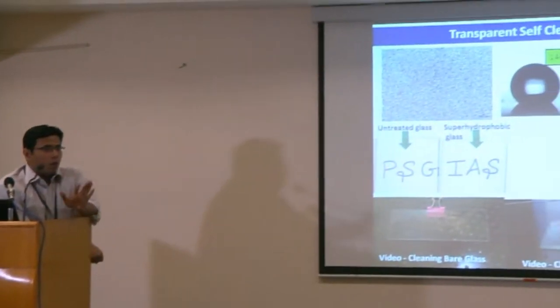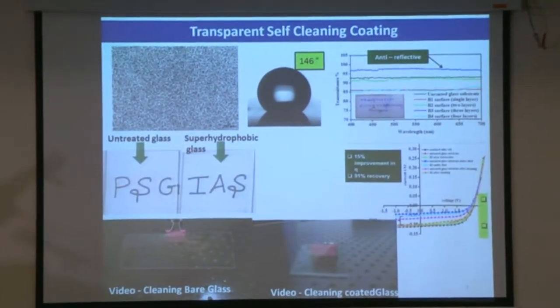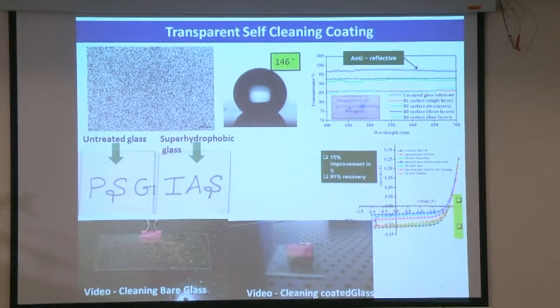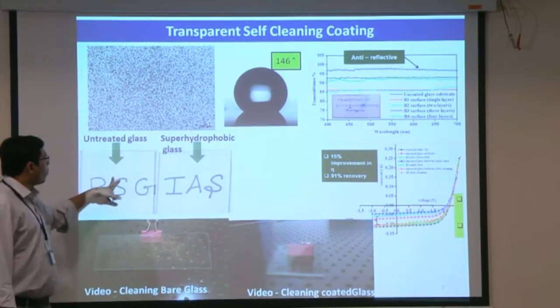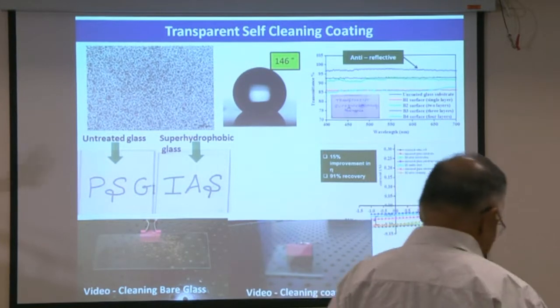What we have done is take a superhydrophobic surface, but simply creating a superhydrophobic surface is not enough. You have to maintain solar panel efficiency without dust disturbing it — that means complete transparency. Most panels today come with anti-reflective coating, so you should not disturb the anti-reflective nature while also achieving self-cleaning. What we could achieve so far is self-cleaning, and the coated panel still shows anti-reflection properties.